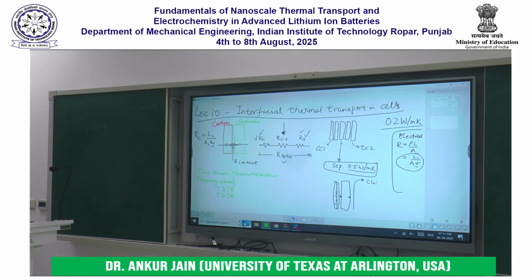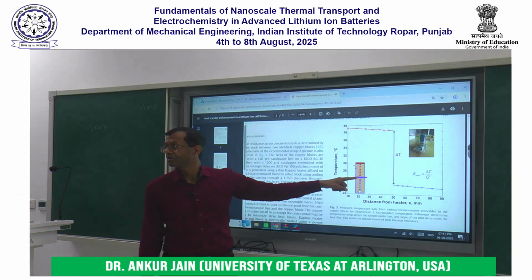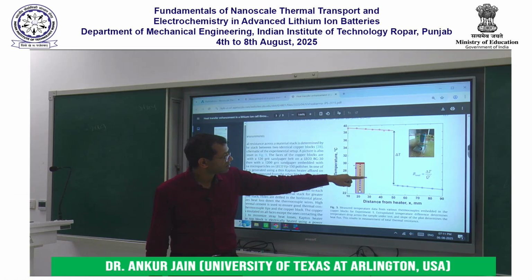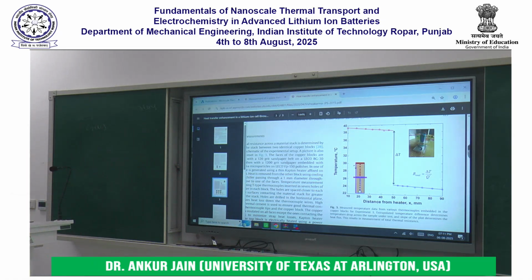We can. So this experiment in which we are doing these measurements, if I take this separator and if I wet it in the electrolyte and put it there, then I can account for the effect of the electrolyte. We had a lot of difficulty doing that. Those were early times. We didn't know how to handle electrolyte and so on, and that electrolyte of course would evaporate and so on. So our measurements were done on a dry sample.